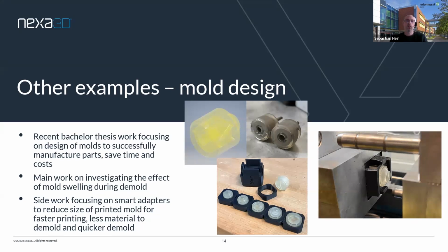And this is the part where it really gets interesting, because we realized how to better design molds, how to approach this. And as you can see in the lower middle picture, of course, we try to minimize the amount of material that we have to remove, because simply put, this material costs money, and the more you have to dissolve, the more material you waste. And of course, it takes longer. So cutting down process time by shortening the demolding step, and cutting down costs by trying to make the parts as small as possible that you have to demold.